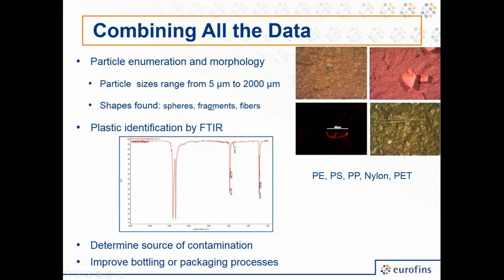In addition to this size range and giving an imagery of what we found, we can also report on what shapes we found. And then if we're able to isolate to larger particles, we can do some spectral identification. So we give a chemical identification, determine and report, was the material polyethylene, polystyrene, polypropylene, or some other type of polymer. Now, whether this data is used by someone for drinking water or bottled water, you can use that information to maybe come up with a way of determining what is the source of that contamination.